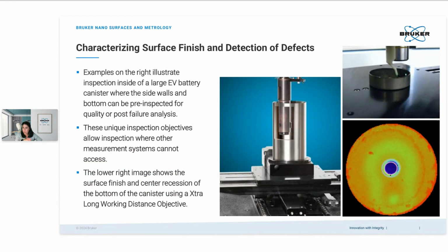The next example on the surface finish illustrates the measurement of large EV battery canisters. The surface finish of the sidewalls as well as the bottom of the canisters has a direct impact on the functionality, but is very difficult to access with metrology systems. What we can do is use unique objectives. For example, as you can see here in the right-hand picture, a so-called borescope objective, where you can access directly into the canister and then measure the vertical sidewall of it and check on its surface finish.